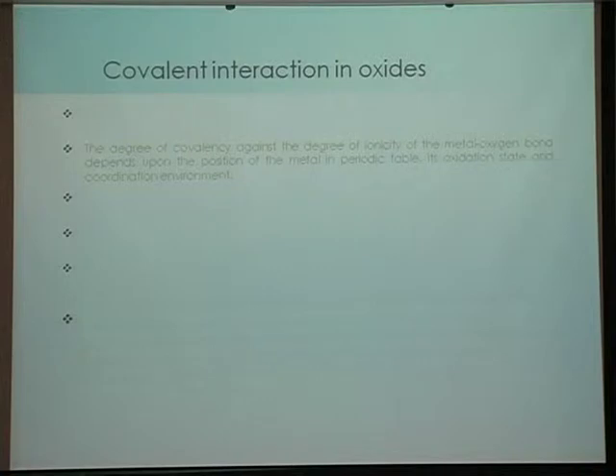But in reality, what one often observes is that it's not the case. There is some charge redistribution. You will probably find some charge density on titanium out of the Ti4+ d0 configuration. Out of that, you will probably have some reduced charge on oxygen and things like that. And that's the covalency part that comes in. Now, in any metal-oxygen bond, what is the degree of covalency and what's the degree of ionicity? That would depend upon the position of the metal in the periodic table, its oxidation state, and more importantly, its coordination environment. And I'll try to show you why.